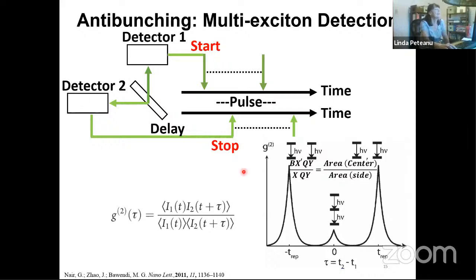Now, what the data ends up looking like, if you have pulsed excitation, which is what we have, a laser pulse that's about 100 picoseconds long with a repetition rate in the 40 megahertz range or so, is that you'll get a burst of emission every time you have sequential absorption and emission events. So a photon is absorbed and emitted at the repetition rate. But at the center here, where the time delay is zero, you'll get essentially zero intensity if the molecule cannot absorb and emit a photon within the laser cycle. It cannot do that more than once.